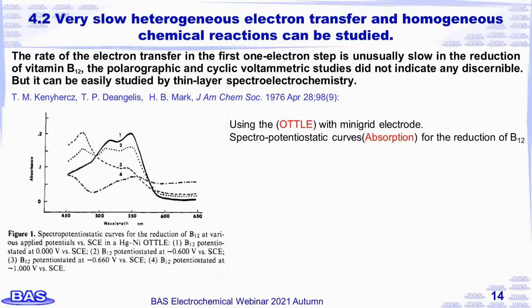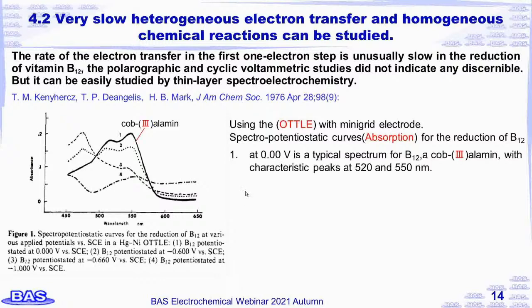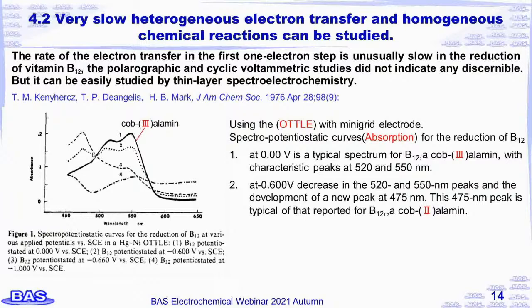Potentiostatic curves for the reduction of B12 are measured using the OTTLE with a mini-grid electrode. Absorbance at different potentials was recorded first. Curve 1 at 0 volt is a typical spectrum for B12a, a cob-(III)alamin, with characteristic peaks at 520 and 550 nanometers. Curve 2 is at minus 0.6 volt, with a decrease in the 520 and 550 nanometer peaks and the development of a new peak at 475 nanometers.